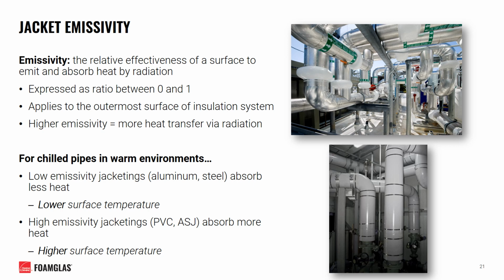The higher the emissivity, the more heat transfer will occur between the material and its environment via radiation. When considering chilled water pipes in warm environments, low emissivity jacketing materials, such as aluminum and steel, will absorb less heat from their surroundings via radiation, which will result in a lower jacketing surface temperature. Conversely, high emissivity jacketing materials, such as PVC and ASJ, will absorb more heat from their surroundings, yielding an overall higher surface temperature for the same system.